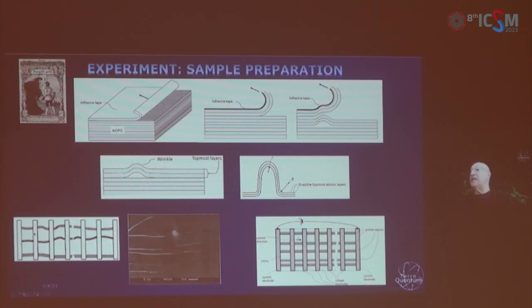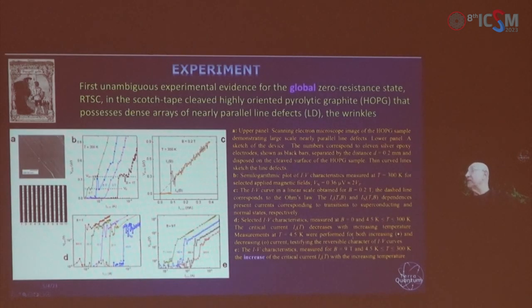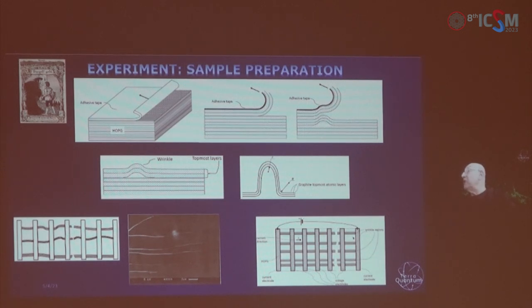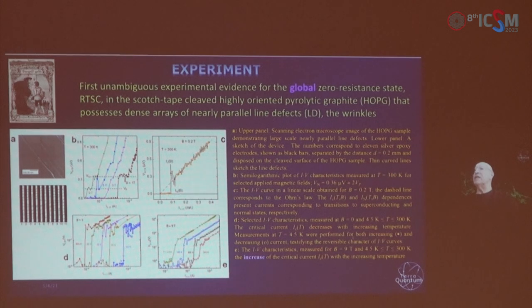Well, and this is the scheme of the experiment. Those are the schematic sketch of the electrodes, these bars, and those are the schematic sketch of the wrinkles going along the samples, and this is the SEM picture of these wrinkles, and this is a scheme of the measurements. So we actually measure the global voltage between the first and the last electrode, and we make measurements of the local voltages between, for example, the 10th and 11th electrodes, and also between different other electrodes. And this is basically key.